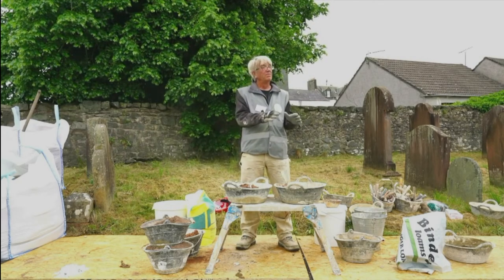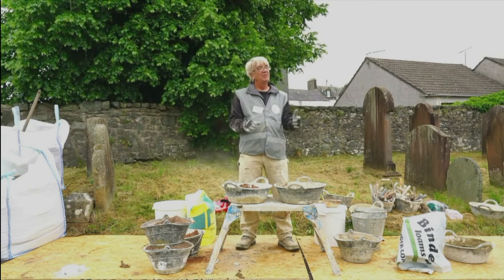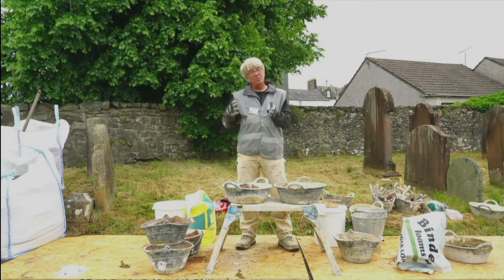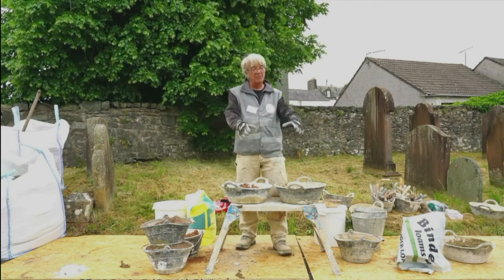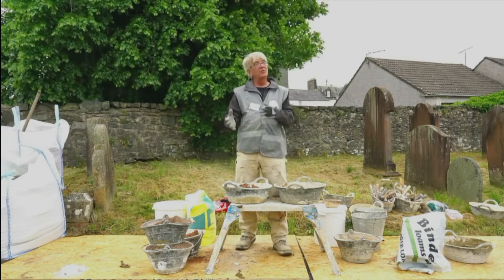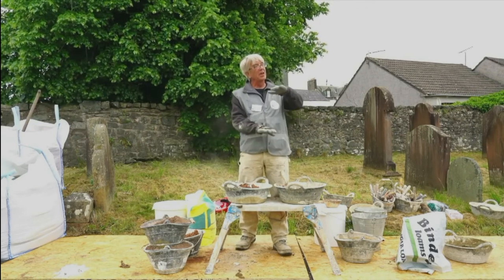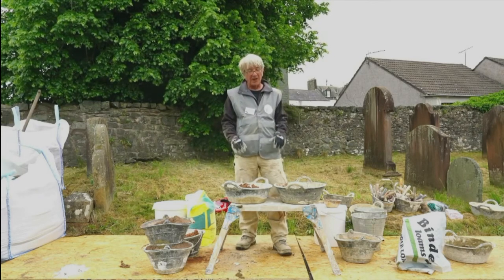So that's the problem. If you were to actually add boiling water in that scenario, no issue, because boiling water wouldn't chill the lime. But similarly, if you put too much water, like if you make lime putty by throwing lump lime into huge volumes of water, it'll run to a paste, it'll run to a liquid, it'll slake, but you've drowned that. It won't reach a temperature that it needs to reach.